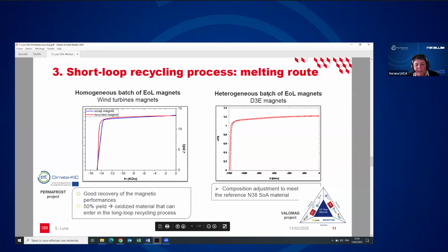Another example is a heterogeneous batch of end-of-life magnets, where by a composition adjustment, we can meet the reference N38 state-of-the-art material. And these results have also been obtained within an EIT RawMaterials financed project. What I did not say in the first case is that at the time of the project, the yield of the process was about 50%, but we have to know that oxidized material can enter a long loop recycling process.